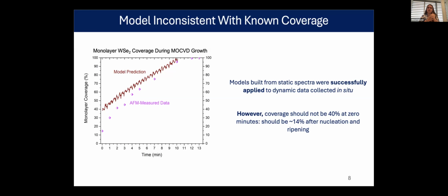We do see that it doesn't agree as much at the low coverage end. We would expect, because we start this SE after nucleation has begun and when we're in that lateral growth step of MOCVD, that it's starting with maybe 14% coverage, and the model only starts showing up at 40%. So there's some disagreement there. So we have to ask what could be going on. So I did an investigation.